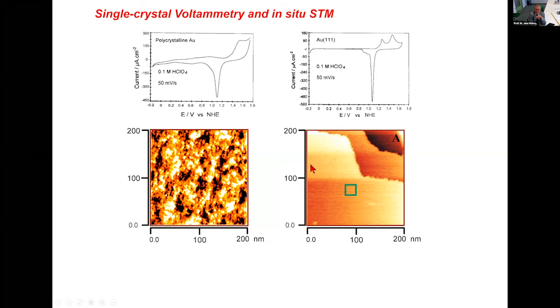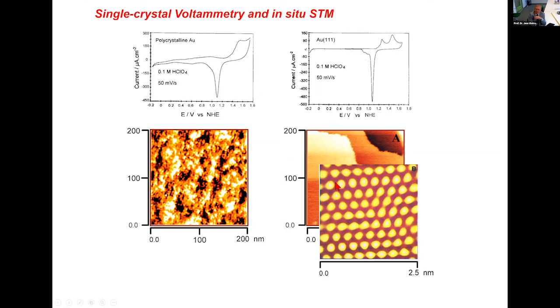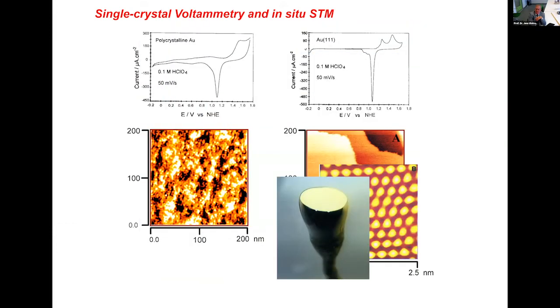Whereas if you go to the single crystal electrode surface, first of all, you can see almost with your own eye, or at least using electrochemical scanning tunneling microscopy, it looks much smoother. Here are some step edges, and here you can see the voltammogram, which looks much prettier than on a polycrystalline surface. If we zoom in, then we can actually see the individual gold atoms directly in 0.1 molar perchloric acid. And if we zoom out, you can see the electrodes we can use. These are the little bead electrodes that we prepare ourselves in the lab.